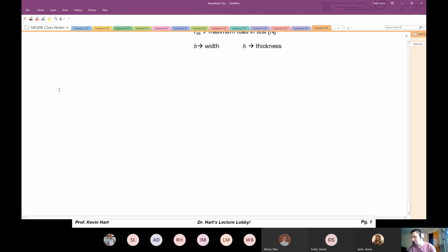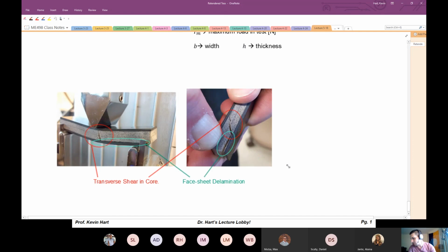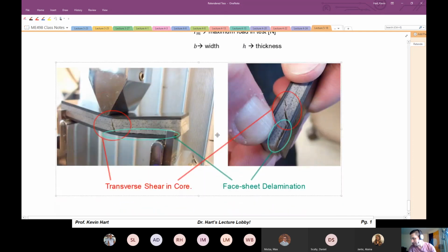There are some pictures here of some samples that I had worked on in the past, just to show quickly and highlight this general idea. Here's a short beam shear test on the left-hand side, with carbon fiber face sheets and a balsa wood core. What you'll notice is that there's some transverse shear going on in the core. You see this 45-degree angle indicating that there's shear present. And you can see the delamination between the core material and the face material. It's highlighted a little more in this image on the right-hand side, this face sheet delamination. This is typically how these core composites will fail.